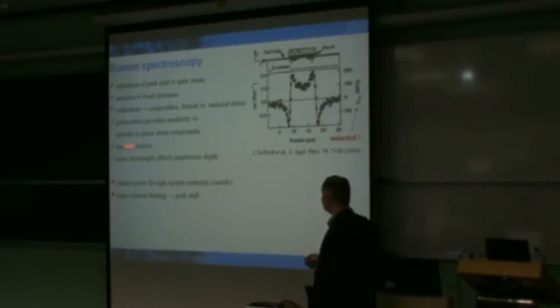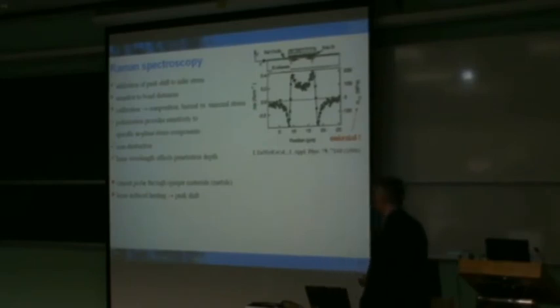Okay, Raman spectroscopy, I mentioned before, where we're looking at changes in the peak shift from a signal that are related to the stress distribution. There is an ability to exploit the polarization of the incoming and exit radiation to look at specific in-plane stress components. It is non-destructive. The laser wavelength can be chosen, too, to look at different penetration depths. And so if you use a UV-based laser, you're much more sensitive to surface distributions as opposed to those that use infrared or other techniques.